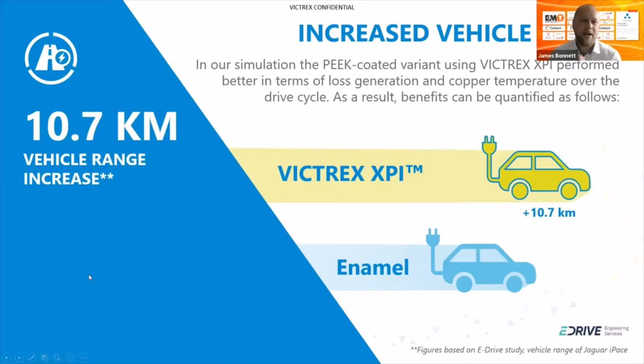So what we're doing here is looking at if we take the assumption that all the energy that's saved from having a lower loss electric machine with XPI coating can be used back into traction and drive force, with 2% energy saving, we can actually increase the range of that vehicle by up to 10 kilometers.